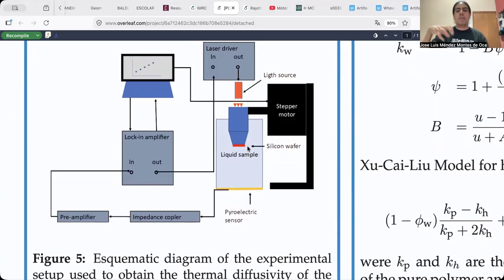And the silicon wafer can be immersed into the liquid samples using a stepper motor. At the bottom of the liquid sample, a pyroelectric sensor is placed to obtain the information of the thermal waves as current information, as an electrical signal. And the signal is sent to an impedance coupler and then to a preamplifier, and then is sent back to the lock-in amplifier, which makes an operation between the measured signal and the reference signal to avoid the noise and obtain a clean signal.